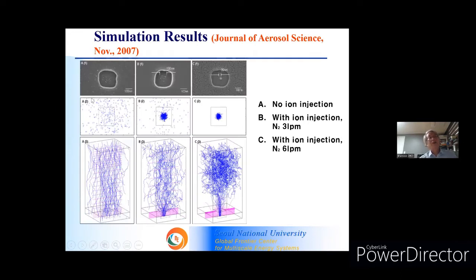Without ion injection, there is no focusing lens, so particles deposit randomly due to Brownian motion. But when you increase ion flow rate to 3 LPM, charged aerosols tend to be confined within some region. At 6 LPM, initially there is random movement, but when these charged aerosols approach the surface, they feel the existence of the electrostatic lens, and they are focused to deposit only at the center region.